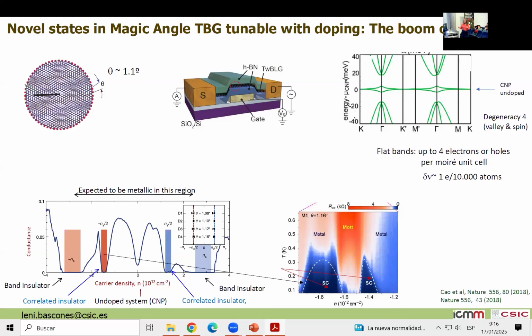And so one thing is that here you have insulating states or resistive states, for this specific case, even if they call it insulating. And you have the superconductivity, and in reality, going from the insulating to the superconducting state just requires adding 1 electron per something like 10,000 atoms. That is extremely sensitive. So this is one of the amazing properties.